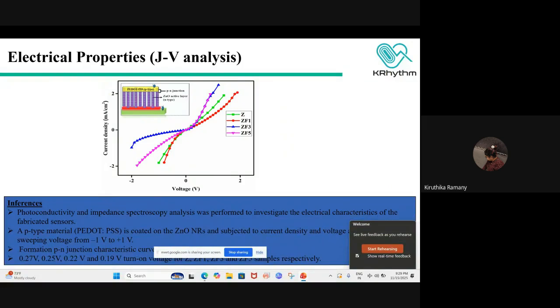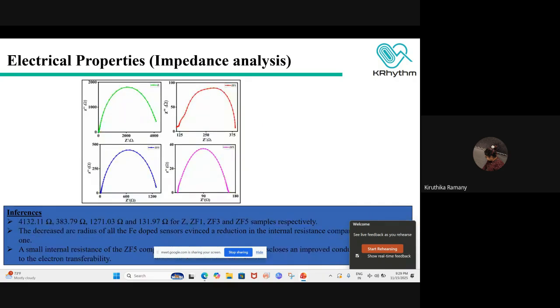Coming to the electrical properties, since we coated PEDOT:PSS above the active sensing layer, we just wanted to find out if it is forming a PN junction. So we went for JV analysis where a PN junction curve was formed, and from this we found the turn-on voltages also. And this is the impedance analysis that we performed. You can see from this picture that the internal resistance of the samples is decreasing as the concentration of Fe2O3 dopant is introduced into the zinc oxide nanorods.